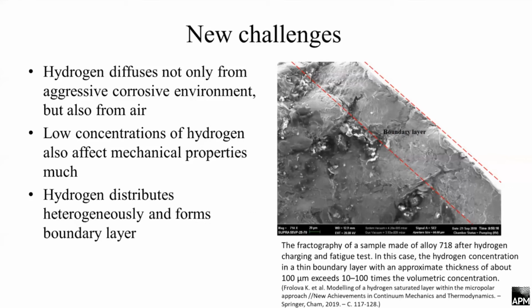And also the last results are the results of hydrogen distribution. A lot of mechanical experiments show that hydrogen distributes highly heterogeneously, and it forms a boundary layer. This boundary layer affects the metal and its properties a lot, because there are experiments showing that when we remove this boundary layer of about 100 micrometers, the metal is not brittle at all and doesn't have the fracture it had. So again, we need a model which explains this boundary layer, how it appears and how it affects the mechanical properties.